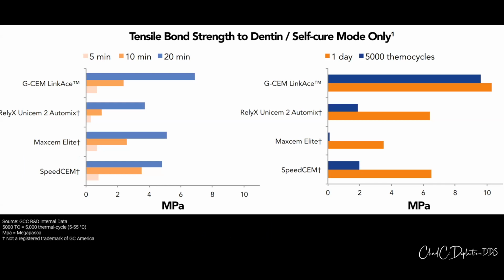Now, when we talk about the tensile bond strength to dentin, what I want you to notice is that for the majority of the cements out there, the tensile bond strength to dentin in the self-cure mode only is going to increase as time goes on. So after 5 minutes, you're going to have a low tensile bond strength. After 10 minutes, that bond strength is going to be increased. And after 20 minutes, it's going to increase even further.